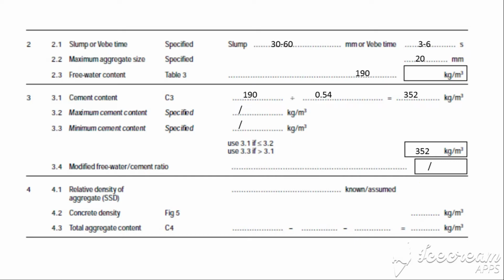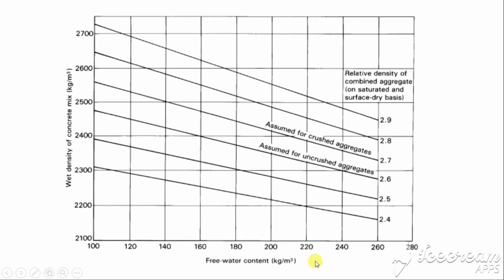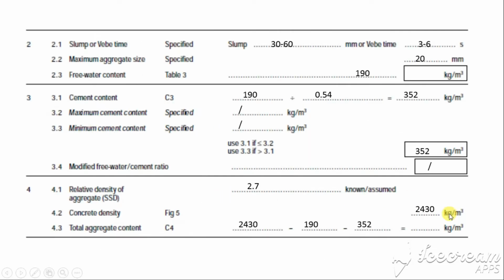And we go to stage 4, relative density of aggregate. We can assume 2.7 if you do not perform any tests for the relative density of aggregate. And then refer to figure 5, you will get the concrete density 2430. How do you get the 2430? This is figure 5. We have free water content 190, project to the line of 2.7 relative density of aggregate, and then from this line project to the y axis. You will get 2430 for the concrete density.